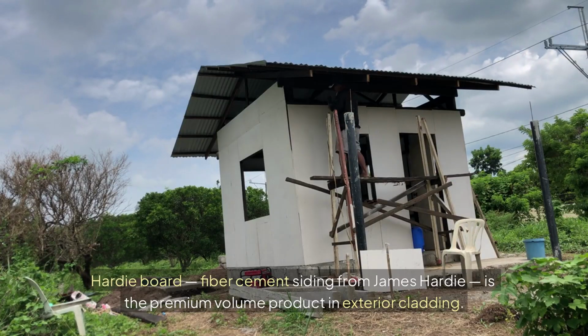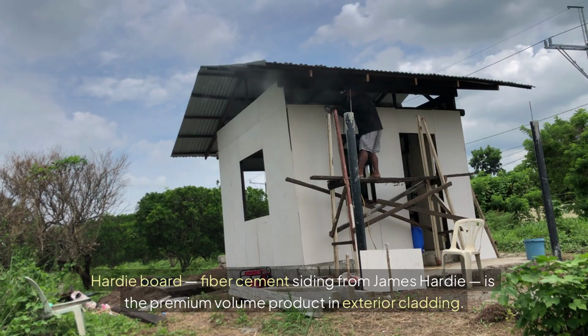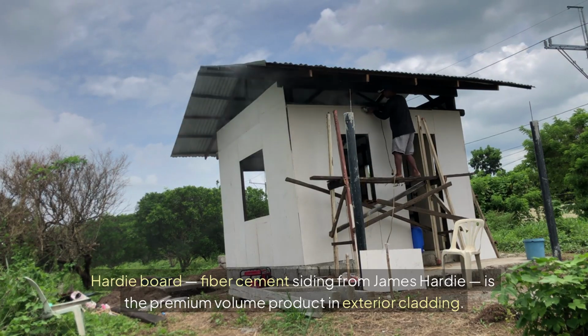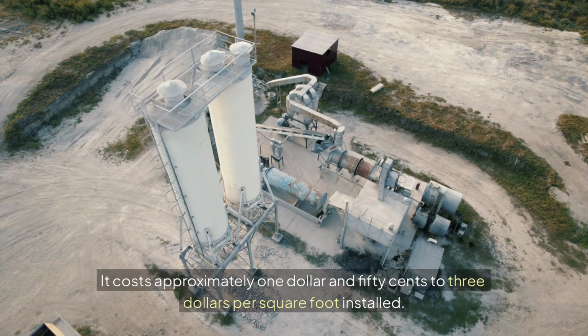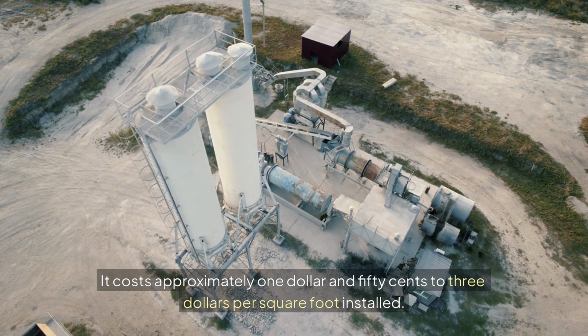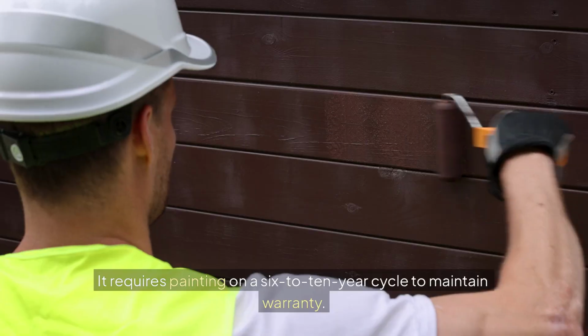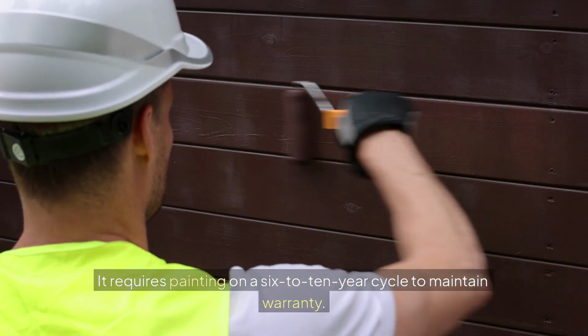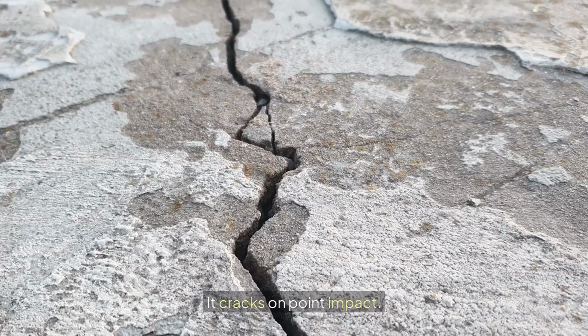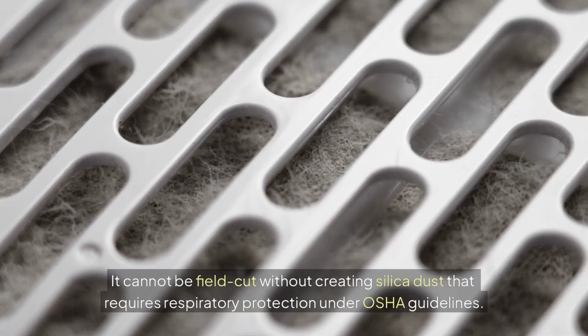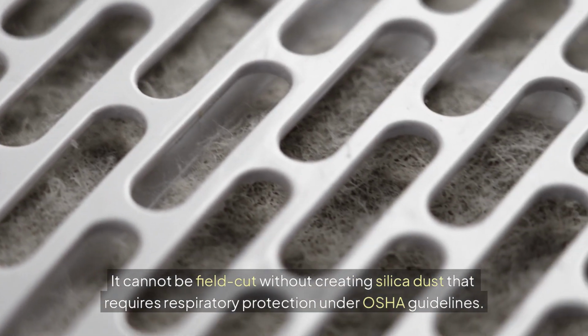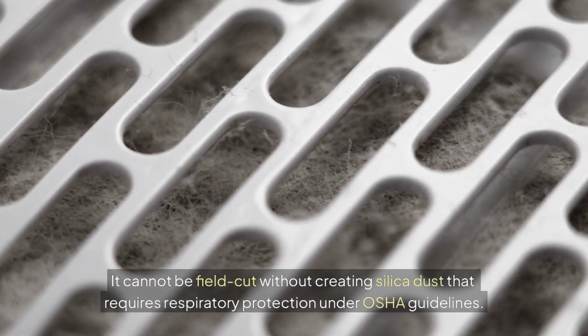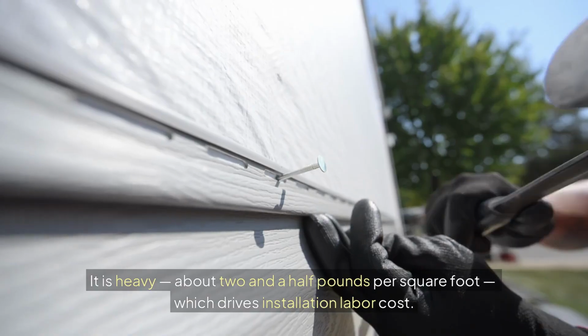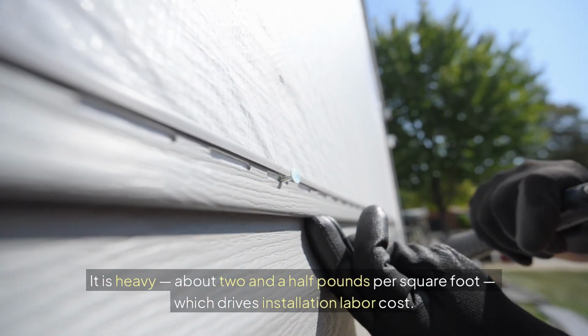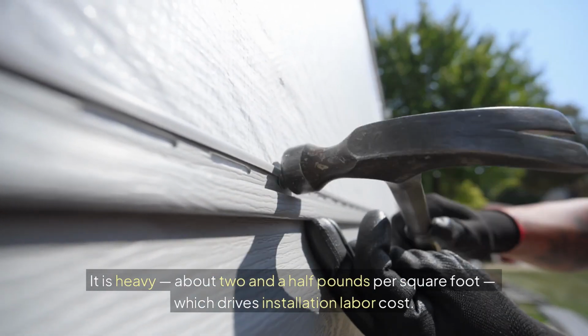Hardie board, fiber cement siding from James Hardie, is the premium volume product in exterior cladding. It costs approximately $1.50 to $3 per square foot installed. It requires painting on a 6 to 10 year cycle to maintain warranty. It cracks on point impact. It cannot be field cut without creating silica dust that requires respiratory protection under OSHA guidelines. It is heavy, about 2.5 pounds per square foot, which drives installation labor cost.